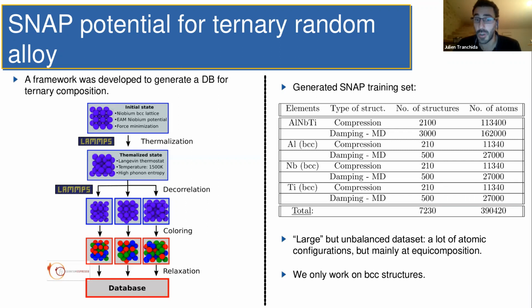Another target material was only composed of BCC elements, and that's why we wanted to get that first step done, basically. So as you can see, the training set is rather large. I mean, you can find much larger training data sets, but it's not small. Especially because all the cells are 54 atoms. So at the end of the day, it's a rather large number of atomic configurations. But it's quite unbalanced too. We have a lot of data at the equicomposition point and not so much outside. So you can't expect an amazing potential from that training set.